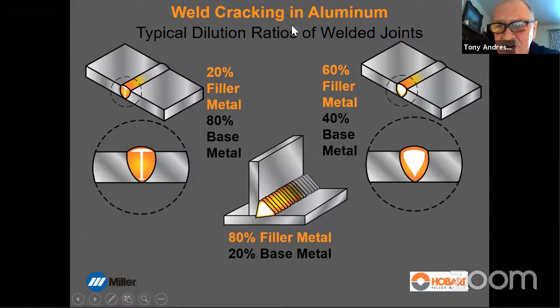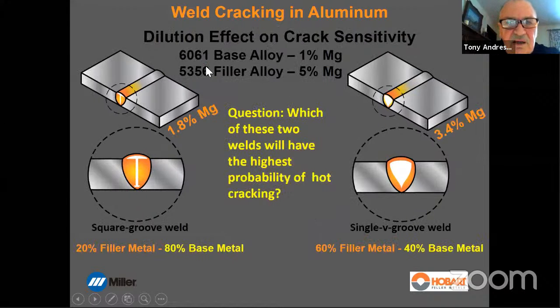If we put a prep on here, we change this ratio. We now have 60% filler, 40% base, which changes the chemistry. 6061 base material has 1% magnesium. 5356 filler material has 5% magnesium. So if we take 20% of the filler metal, which is 5 mag, and 80% of the base material, which is 1 mag, the calculation comes out at 1.8% magnesium in that weld. This molten weld is aluminum with about 1.8% magnesium.